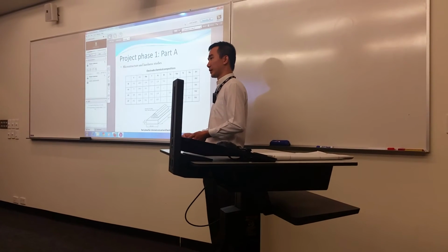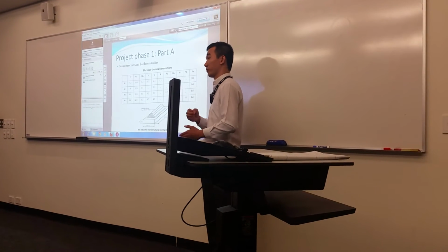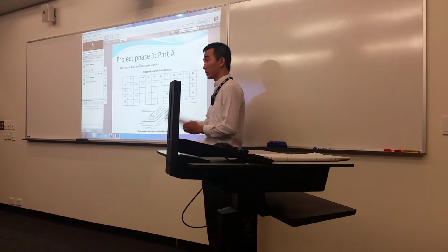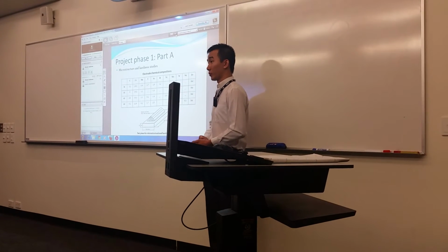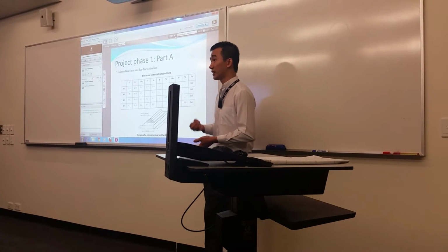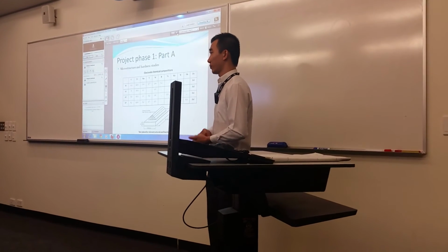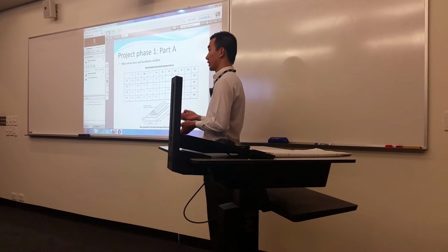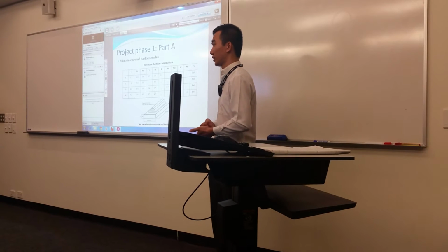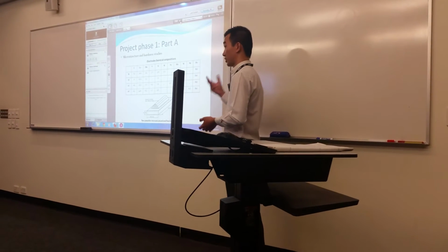Dilution is the phenomenon where the composition of the hard-facing alloy is diluted into the base material, in this case carbon steel, which reduces the chromium content in the alloys, and that reduces the hardness and changes the microstructure of the structure. So the more layers you use in your test piece, the less dilution effect there will be, and you can perform the microstructure and hardness test on the materials.